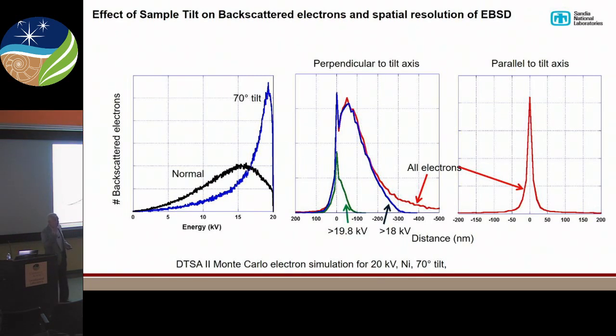So why do we have to tilt? It's a pain, it's difficult, but it really is important. If we look at the number of backscattered electrons versus their energy, we start with a 20 keV beam, and we look at normal incidence, we see that the backscattered electrons that come back out of the sample have this sort of energy distribution. Not very peaked in any direction.